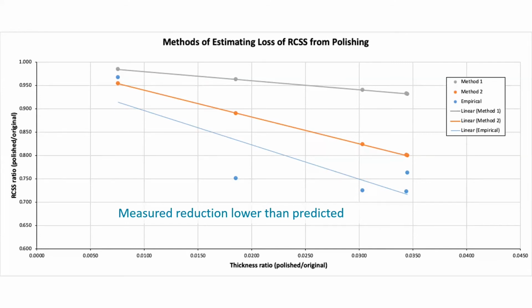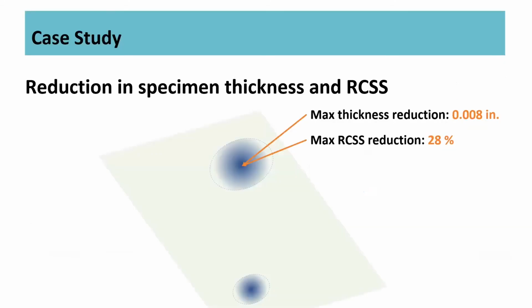All right, so now that we know what the change in the thickness was and what the change in the RCSS is, now we want to go and reapply our glass failure prediction model. Okay, so in this case, we said our max reduction was 0.008, so that's close to that 1/100 of an inch that I was talking about. And we had a corresponding reduction of 28% in our RCSS. So that's a pretty big difference.